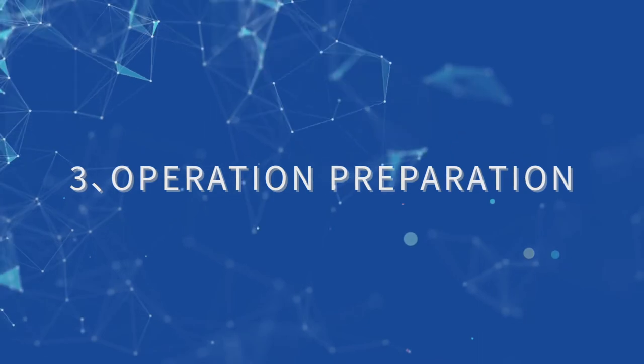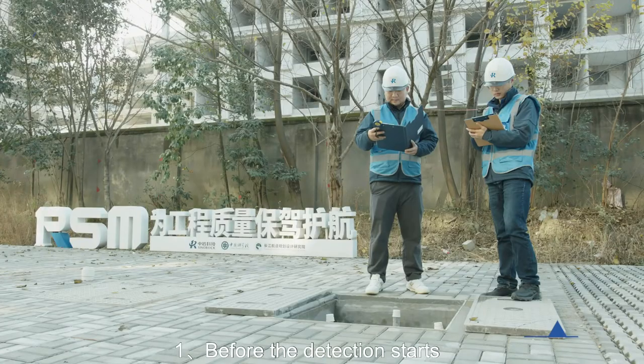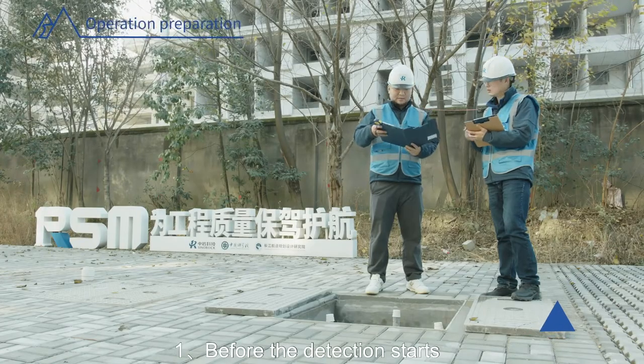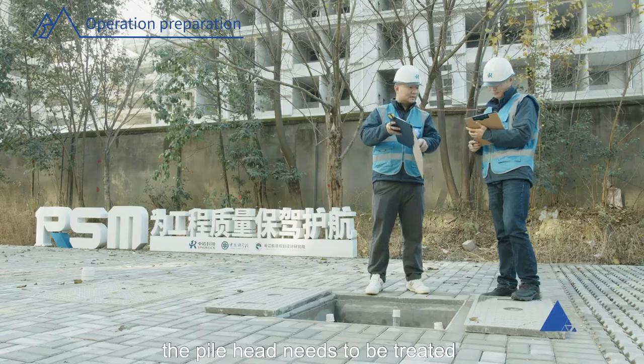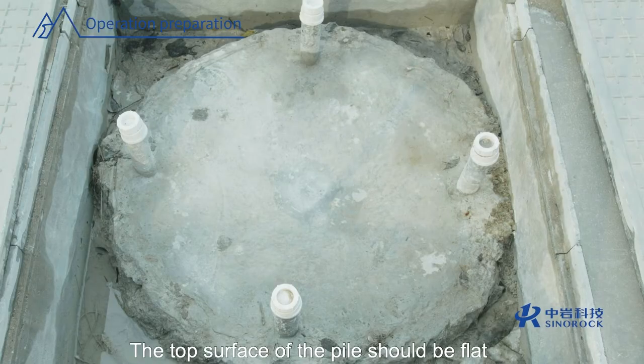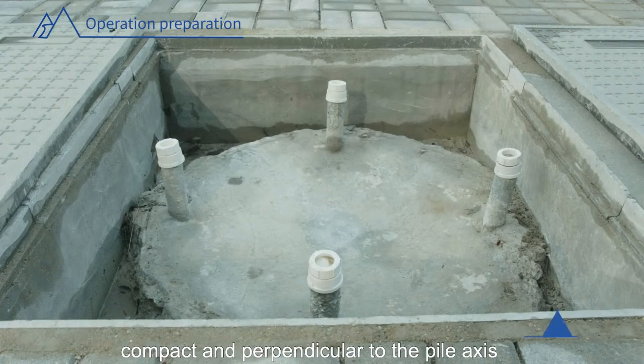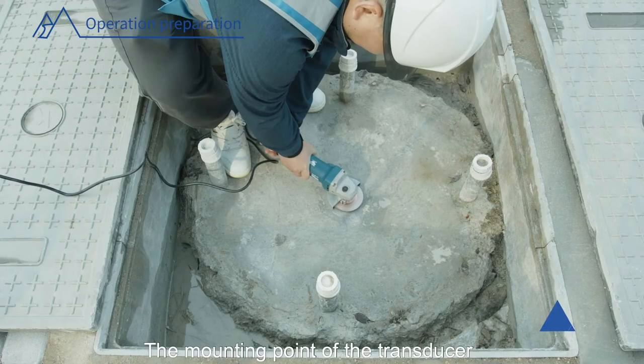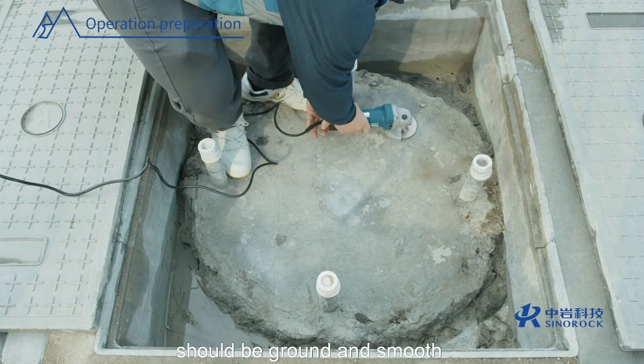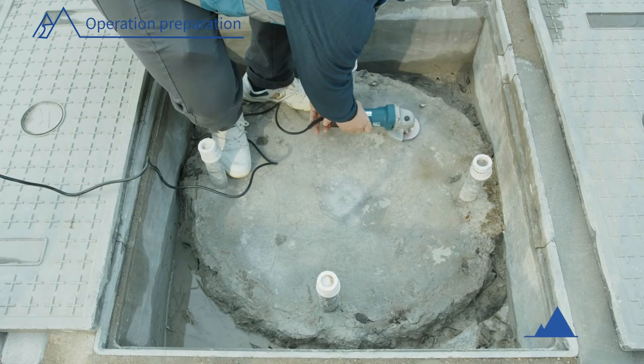3. Operation Preparation. 1. Before the detection starts, the pile head needs to be treated. The top surface of the pile should be flat, compact, and perpendicular to the pile axis. The mounting point of the transducer and the tapping point should be ground and smooth.